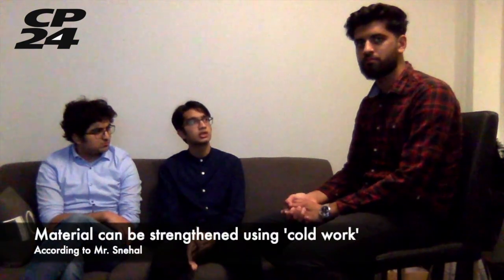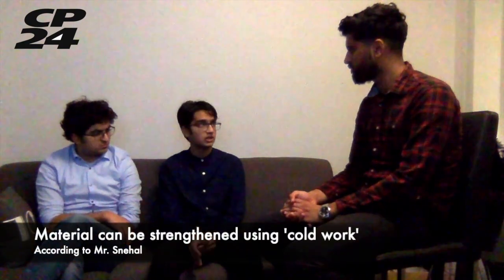Instead, it's cold work. Cold work involves plastic deformation of the metal below the recrystallization temperature. And the cold working of austenitic stainless steels can partially transform the austenite to martensite, which is ferromagnetic, at the sheared and sharp corners, which is followed by annealing in the mill. The degree to which this occurs depends on the composition of the austenite stabilizing elements.